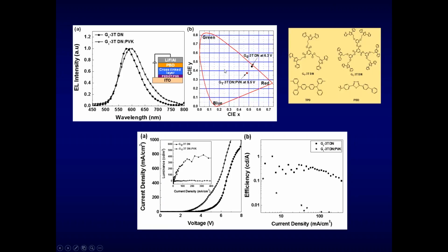Now, these are basically light-emitting diode devices that are orange in color, as shown here. The EL spectra shows fluorescence, or emission, at around 600. And again, the charge current density and efficiency for the crosslink system is shown here. So what I've highlighted here is that dendrimers can be utilized to prepare electroluminescent devices.